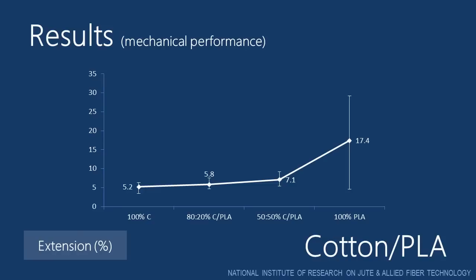Percentage extension of different yarns at break was plotted. The lower level of extension recorded in case of cotton-PLA blended yarns clearly suggests the tensile behavior. Lower extension means that yarn break was recorded once the cotton component was ruptured. A very marginal increase in extension from the 100% cotton yarn sample suggests a very low assistance of PLA fibers in the tensile performance. Extension value of 100% PLA fiber yarn is significantly higher, up to 17%. Higher twist levels have prevented the yarn from reaching the normal level of extension, which is around 23–25%. We can also observe a very high variation in extension values, due to the fact that 100% PLA fiber yarn shows more thin places compared to other yarns. These thin places act as weak spots and result in high variation in recorded data.